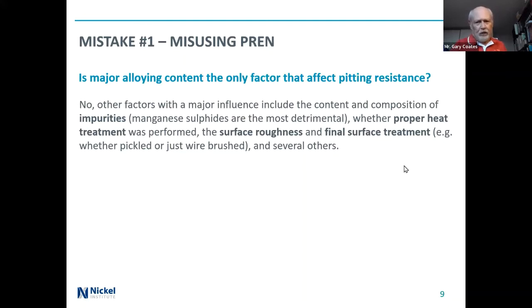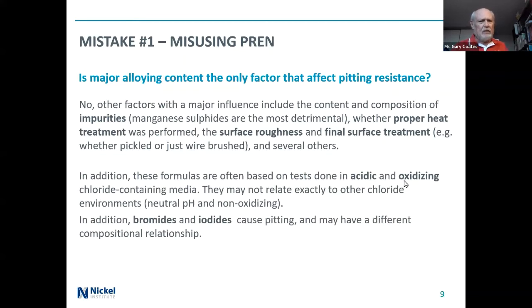The surface roughness and the final surface treatment, whether it was pickled or wire brushed or just left as is, that all affects the pitting resistance of a particular piece of metal. So in addition, we can say these formulas are based on tests done in acidic and oxidizing chloride containing media. They may not relate exactly to other chloride environments. If we have a neutral pH or a non-oxidizing system, these PRE numbers may not relate directly to that. They may not be too far away, but they may not be directly relatable, comparable. And then we have the issue of bromides and iodides, which can also cause pitting, and there it doesn't relate whatsoever to the PREN in any specific way, although it is somewhat related, but I would never use PREN to decide what to use in a bromide or iodide containing environment.